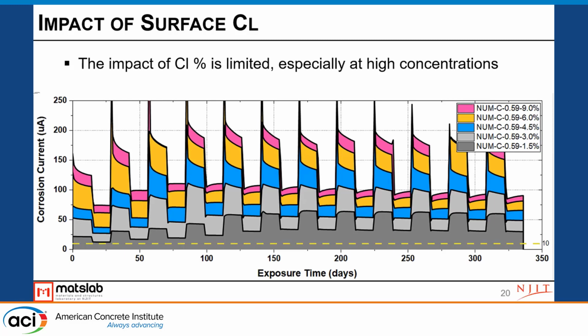What it tells us here is, of course, we get higher corrosion possibility when we have higher chloride concentration. However, the relationship between these two is not linear. The impact of surface chloride concentration is actually limited when the concentration is high enough.